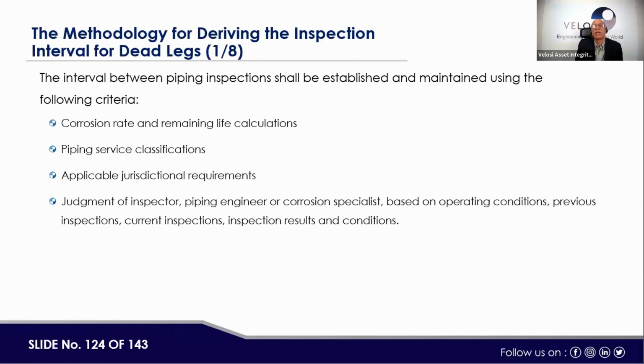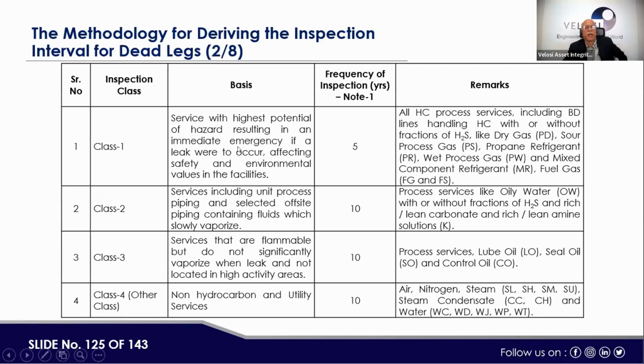Then the interval between piping inspections shall be established and maintained using the following criteria. Just informing you how it is done: corrosion rate and remnant life calculations, piping service classifications, applicable jurisdictional or regulatory requirements, then judgment of the inspector, piping engineer, or corrosion specialist based on operating conditions, previous inspection results, current inspection results, and the actual condition of the piping system. If you see here, the general interval for class 1, class 2, class 3, and class 4 as per API 570 is 5 years, 10 years, and 10 years for the remaining classes. But in this particular case, the client went with a 3-year interval rather than a 5-year interval.